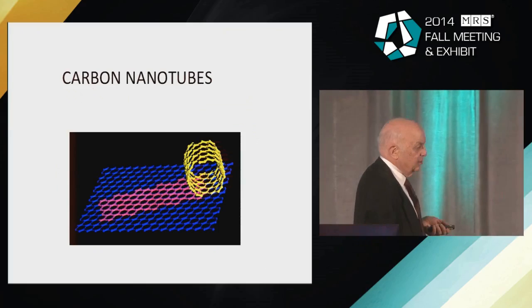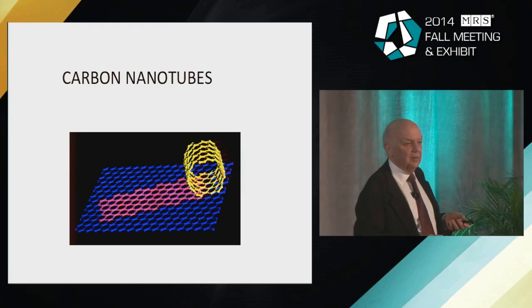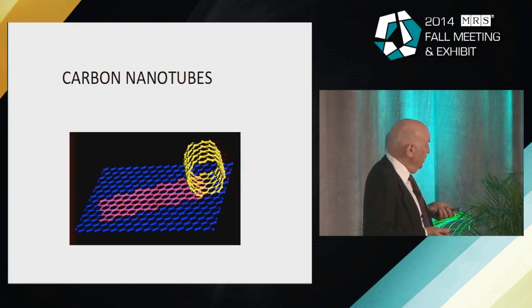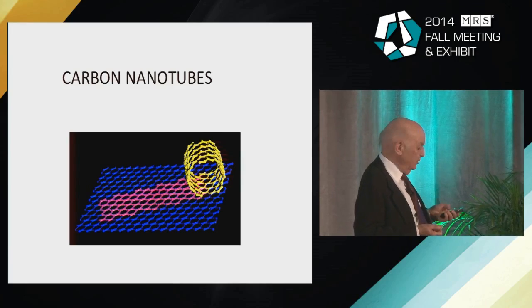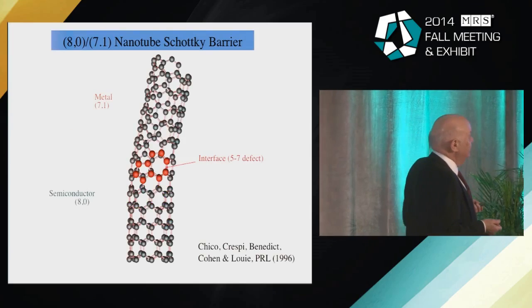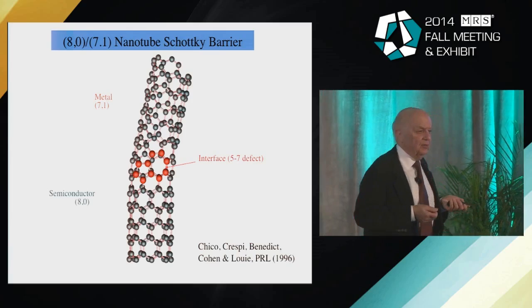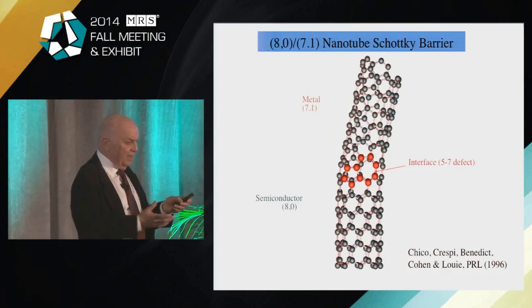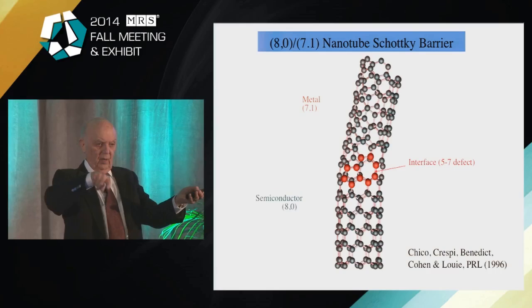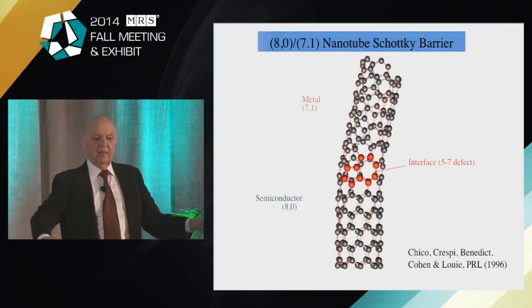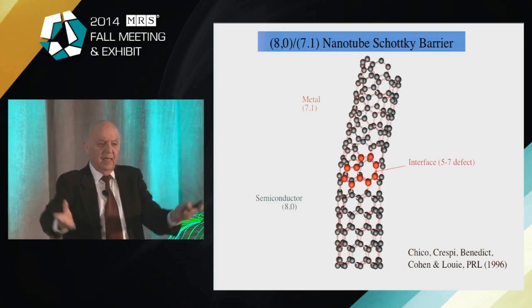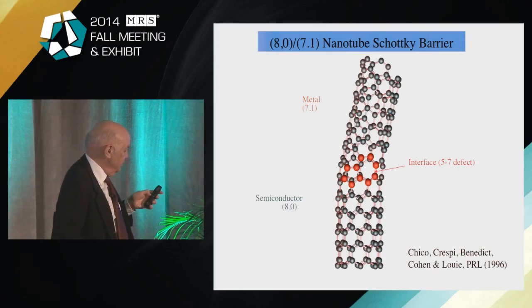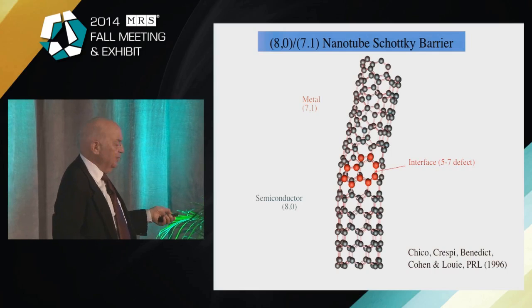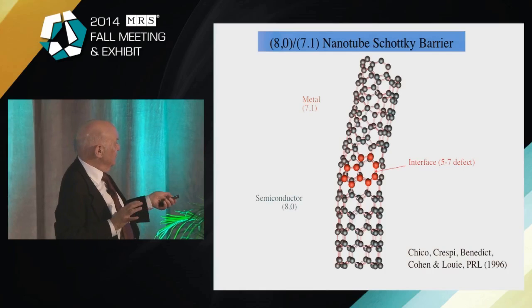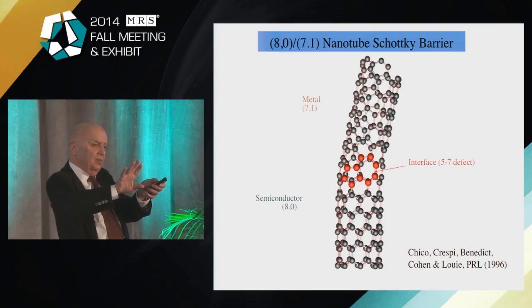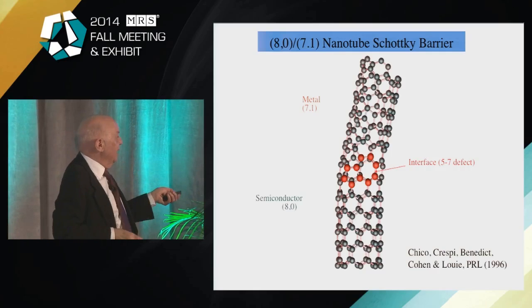So these systems can also be explained using these approaches. And in fact, we know that graphene layers roll up and make carbon nanotubes. And theoretically, you can calculate the properties of these. I'll give you just one example of a carbon nanotube and one example of another nanotube. If you take a sheet of graphene, and so it looks like chicken wire with all the hexagons, and you bend it around so that you go around eight hexagons and bring it back, that material will look like this, and it's a semiconductor. So the 8 refers to the fact that I went around 8 times, but I didn't displace the system. For example, here, if I go around 7 times, but move my hexagons up 1 so they don't match, that material is a metal.